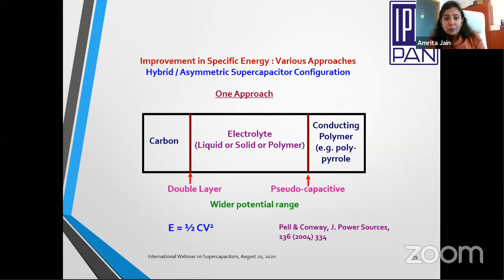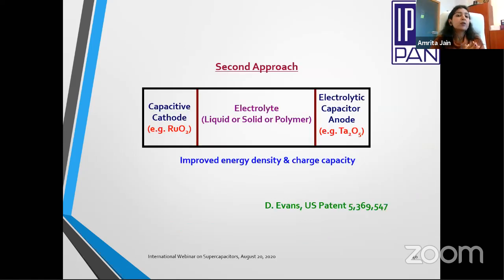Now to improvement, what can be done. There are various approaches. The first approach is to have an electrolyte material, any type, liquid, solid, polymer, and on one side a carbon type electrode, on the other side a conductive polymer electrode. Make sure to have this electrolyte with a wide potential range. Second approach, one side a capacitive cathode, the other side an electrolytic capacitor anode, and then an electrolyte, of course, with a wide range.